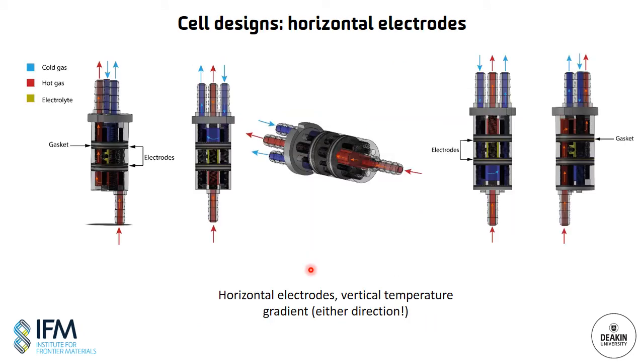The design for the horizontal electrode version is modular and can be set up with a temperature gradient in either direction, so the hot electrode at the top and the cold electrode at the bottom, or vice versa. Though I should note that the hot gas always needs to come from below, and that's because we're using the heater inside our microimaging probe, which is located below the cell, to heat the hot gas. So this modular design allows us to apply that temperature gradient in either direction despite that limitation.